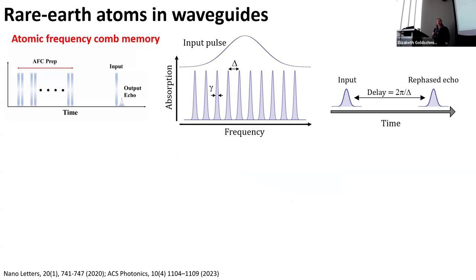So the idea here is we have this inhomogeneously broadened set of thulium atoms. We come in with a train of optical pulses. A train of optical pulses is a frequency comb in frequency space that does spectral hole burning. So everywhere where there's light, it burns away. It puts the atoms into some other state. And so we make a spectral absorption profile that looks like a comb, right? Now, if you send in a pulse whose bandwidth is much larger than these comb teeth, you excite the atoms, you get dephasing of the different teeth relative to each other because of their detuning, but at time equal to 1/Δ, 1 over the spacing between the teeth, they automatically rephase and come back out. So this is why you get to set the memory time in advance by controlling what this dephasing is. Right.